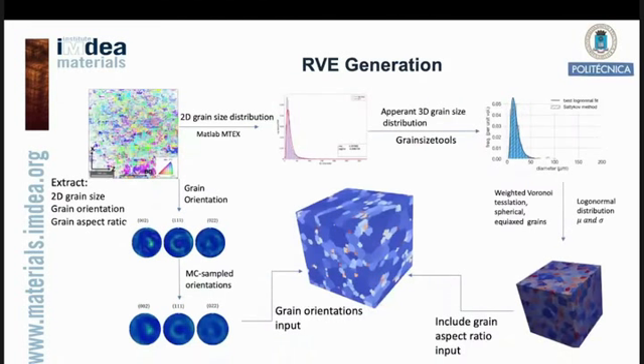Then the first ingredient to our work is the RVE generation, which is the most important work. Since we have the EBSD, and as I said earlier, that we have elongated grains in one section, we extract three things from the EBSD. One is the 2D grain size, second is the grain orientation, and third one is the grain aspect ratio. Using the 2D grain size, since we are using MATLAB MTEX, we get the 2D grain size distribution. We generate the apparent 3D grain size distribution using DREAM.3D or other tools, considering spherical grains.